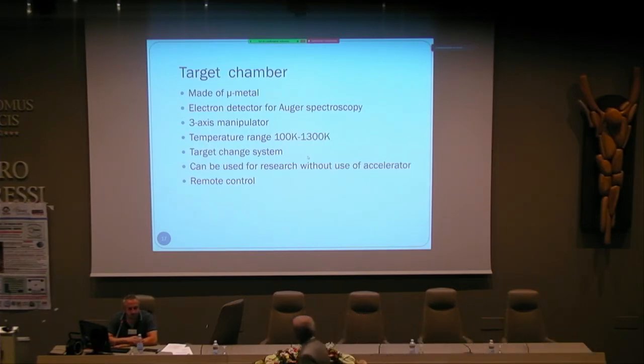Okay, thank you very much, very interesting. I have a question regarding contamination. My experience with contamination is that most of the time it happens by the beam itself, because the beam will crack the oxygen molecules, so it will produce oxide on the surface. So if you translate your sample, do you have a cleaner surface there or not? We can use, for example, argon to clean the surface.